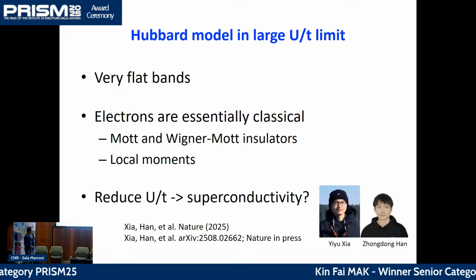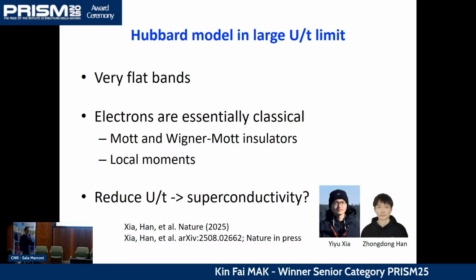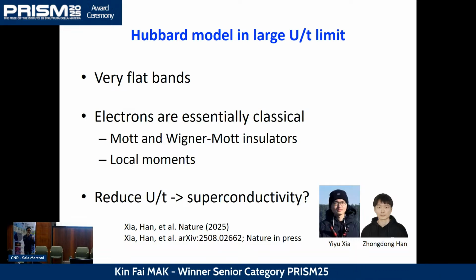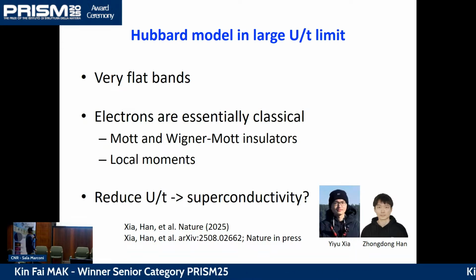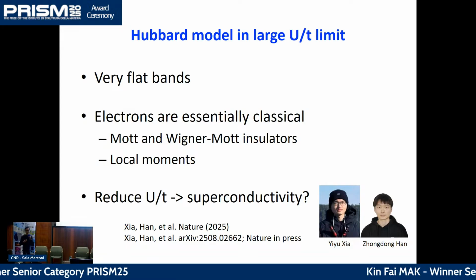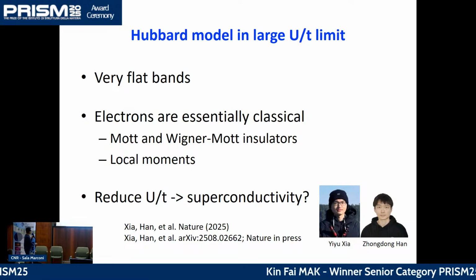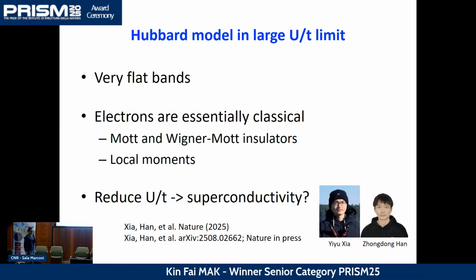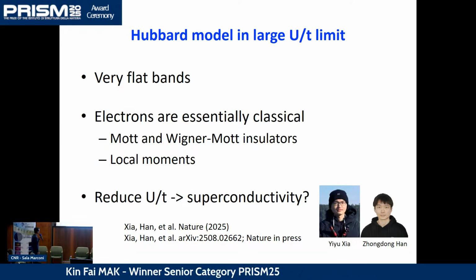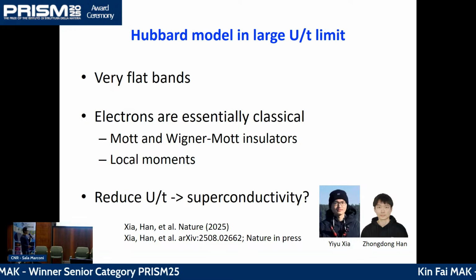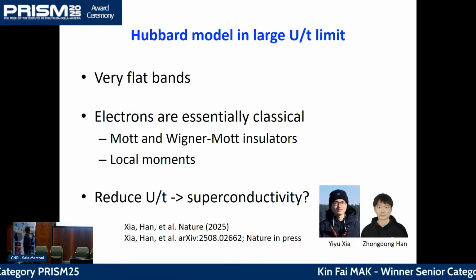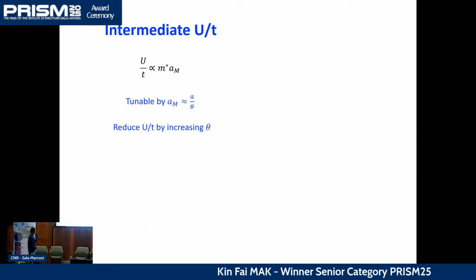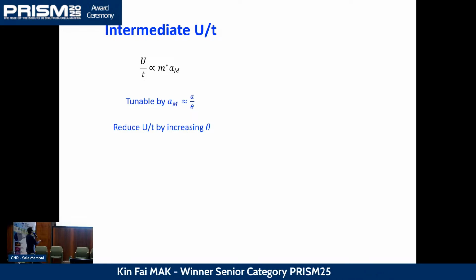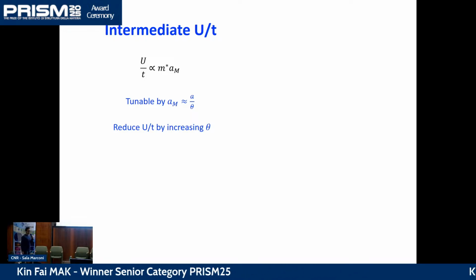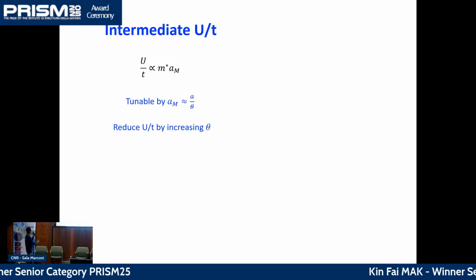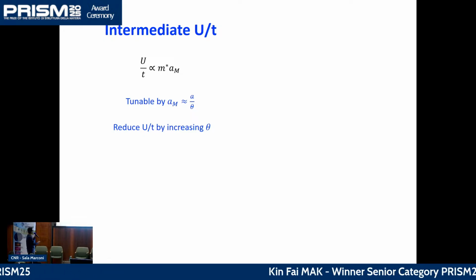But on the other hand, if you want to create superconductivity, you would like the electrons to be more quantum mechanical. To make the electrons more quantum mechanical, you want to increase the kinetic energy and, as a result, reduce the U over T ratio. Maybe then you get a chance to induce superconductivity in the system. That's something that I want to very briefly highlight. Indeed, by doing that, we can get a superconductor out of the system. So the idea is to reduce the U over T ratio. And if you remember from a few slides ago, the U over T is proportional to the moiré period.